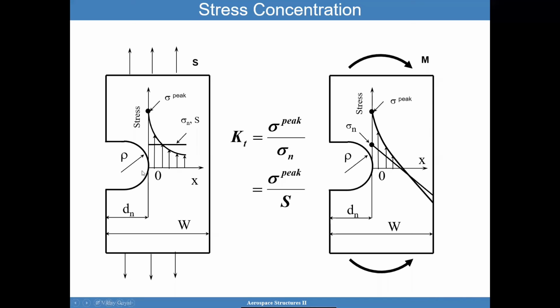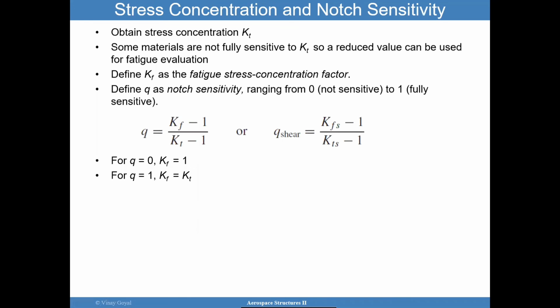So given a stress concentration, you want to look at calculating Kt. Kt is the peak stress divided by the average stress across this part, or sigma peak divided by S, the far field stress. That's your peaking factor or your stress concentration factor. Then you're going to obtain the notch sensitivity. The idea is that a stress concentration factor is going to have a notch sensitivity, and we want to find out the fatigue stress concentration factor due to that notch. And I think this becomes very important.